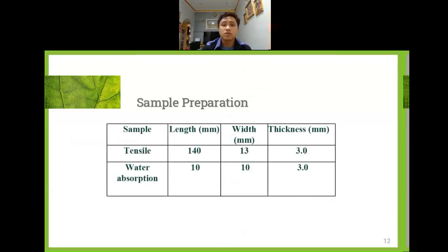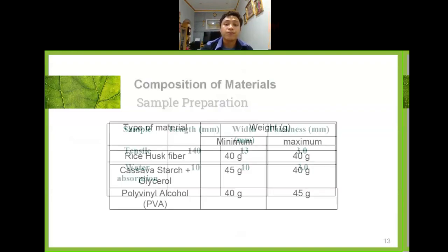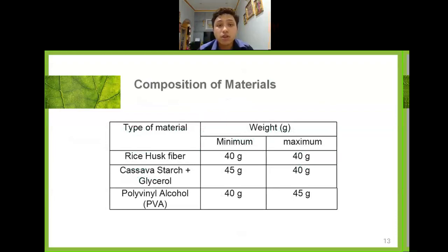And then we go to the next slide, sample preparation. For the tensile specimen, the length used is 140 mm, the width is 13 mm, and the thickness is 3.0 mm. That I use from the ASTM. I follow the ASTM. And then for water absorption, I also follow the ASTM. The length is 10, the width is 10, the thickness is 3.0.